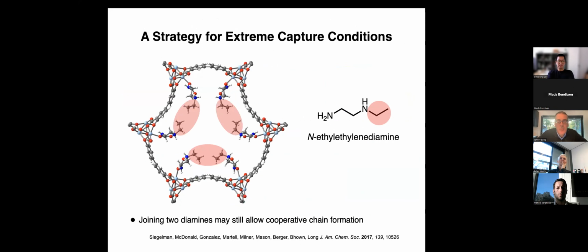So one thing that we've had in terms of projects for a long time is we've worked with ExxonMobil on trying to create a MOF that could do cooperative CO2 capture at high temperature conditions from a natural gas fired power plant flue gas. And so that's a concentration of around 4% CO2. But they also had a process where they wanted to use these at high temperatures, where you could capture at high temperatures and minimize this water coadsorption from the flue gas.